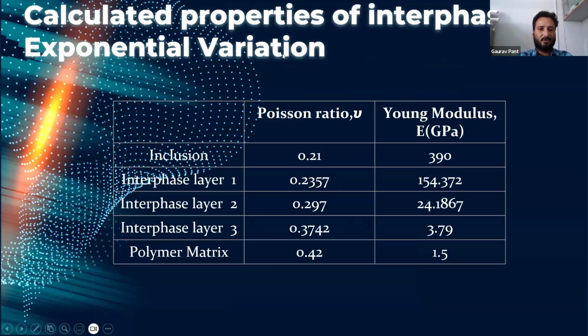These are the properties of the interface calculated by this mathematical model, how the properties of the different interface will be obtained. You can see the inclusion is having Poisson ratio 0.21 and Young's modulus 390, and the polymer matrix is having 0.42 and Young's modulus 1.5 gigapascal. So there is a huge difference between the Young's moduli.